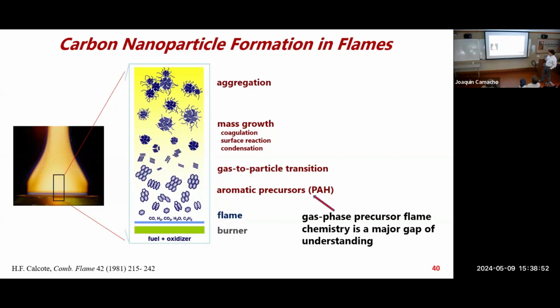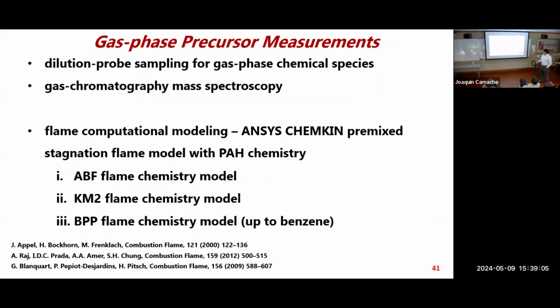So another area that I'm starting, which is very early progress, is measuring and quantifying the concentration of these precursors in the flame. So the chemical species measurements. We use this dilution probe, the same stagnation plane with a probe that will allow us to pull a diluted sample and hopefully quantify the concentrations by gas chromatography, mass spectroscopy.